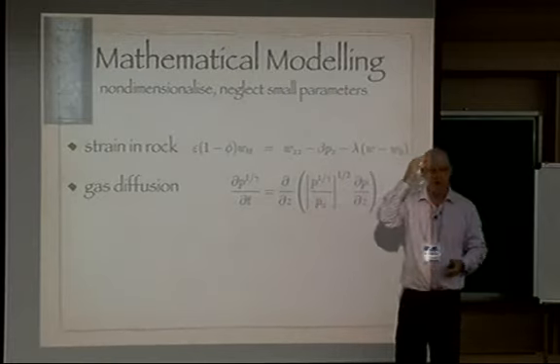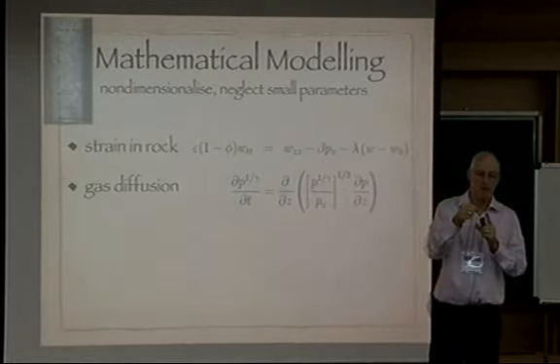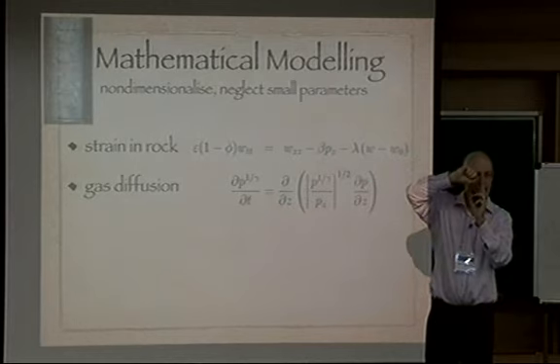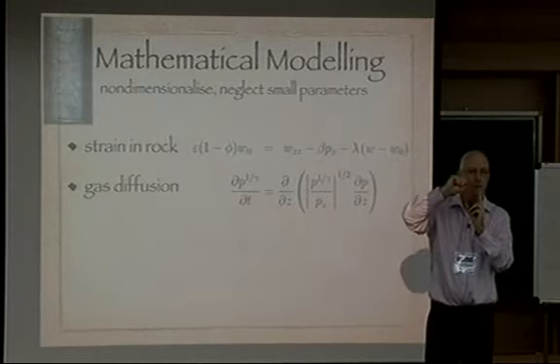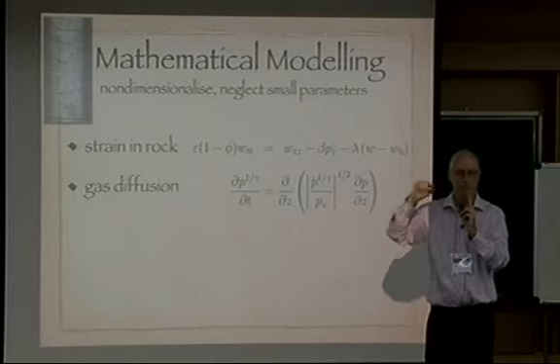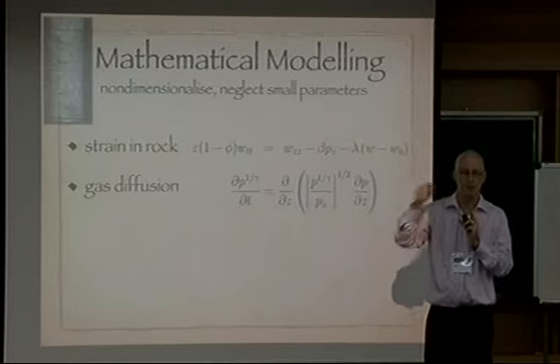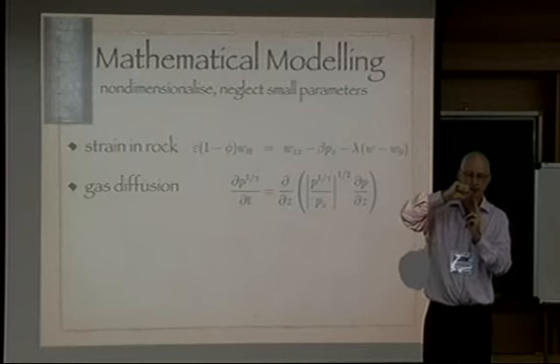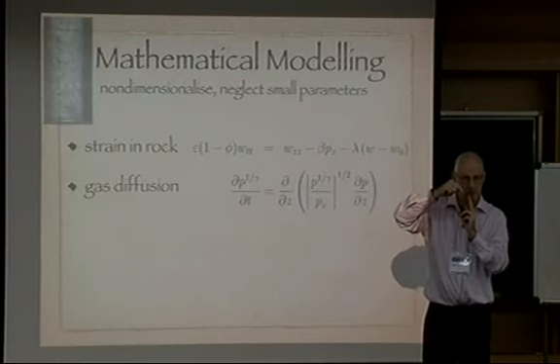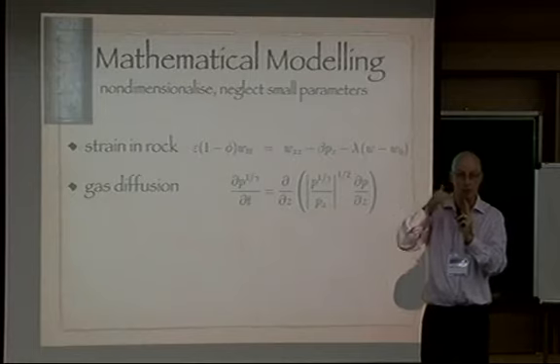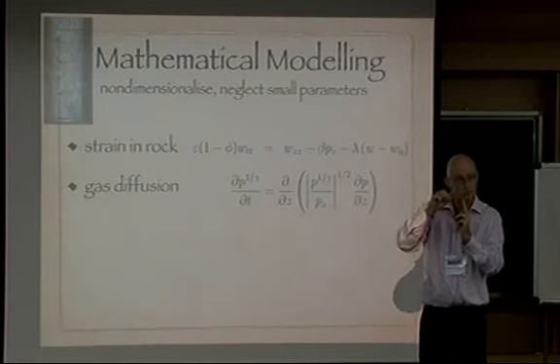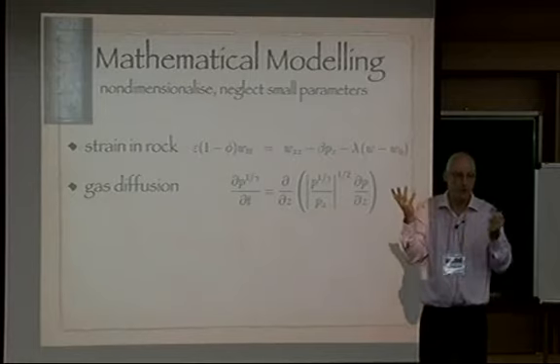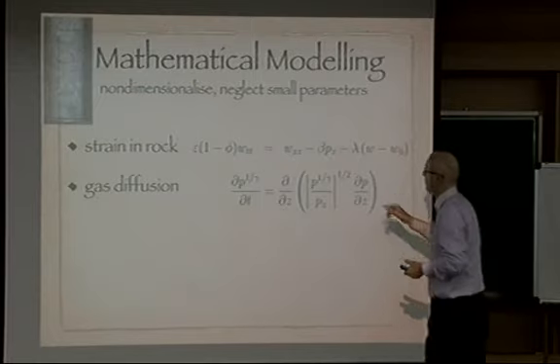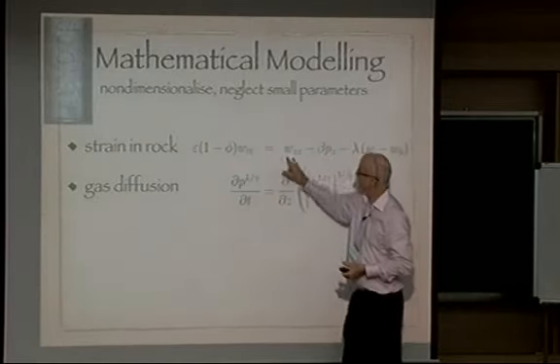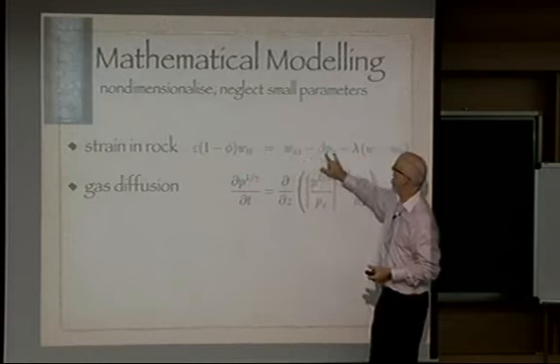It turned out we could relax about the seismic waves because the pressure at the surface, on this time scale, drops quite slowly; it's not an instantaneous drop. We've got a trace of how fast it drops, and it drops exponentially fast, but it drops. Seismic waves, of course, occur immediately and happen very quickly, with very small pressure changes, and they just don't do anything. What is important is if 0 equals this, we then get related stress and strain, and we find R.